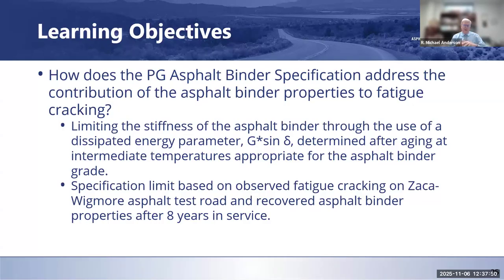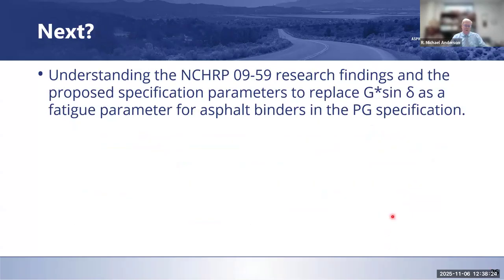That was determined after aging at intermediate temperatures that were appropriate for the asphalt binder grade and the climate in which it was used. And that specification limit that was in the PG system was based initially on the observed fatigue cracking that they saw largely on the Zaca-Wigmore asphalt test road with recovered asphalt binder properties after 8 years in service. It was validated in part through the laboratory experiments that were conducted during SHARP. And ultimately, that's how they came to choose what that parameter was that was used within the current version of the PG system. So what's up next for us?